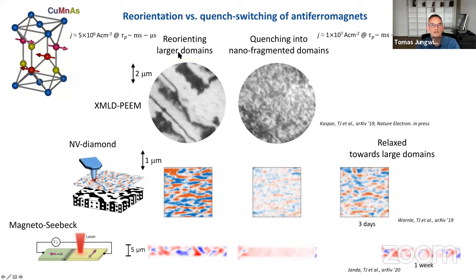Now, when we take the very same device, the very same single layer film copper manganese arsenide, and we apply about a factor of 2 larger current pulses than the minimum pulses for the reorientation switching, we see a completely different picture in the X-ray magnetic linear dichroism microscopy. Instead of seeing reorientation of large domains, we see that we broke our system into this nano-fragmented domain state.